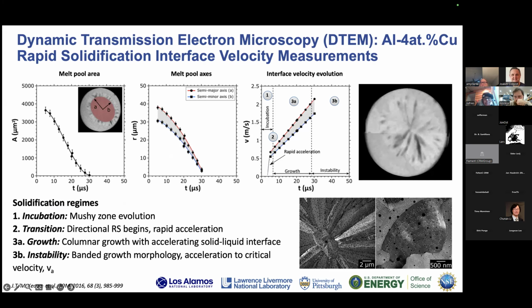And these types of morphologies have been predicted by solidification theory. So here in the central region is this banded growth, and this basically is associated with local acceleration and deceleration of the interface and the local solute conditions that drive this. And so that's been seen with DTEM, which is actually pretty neat.